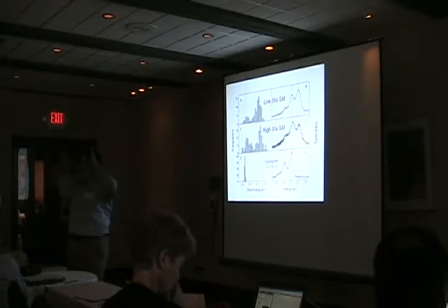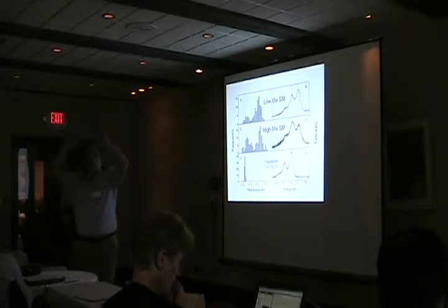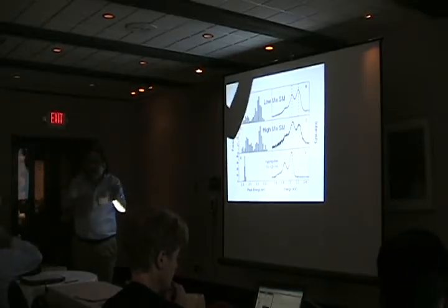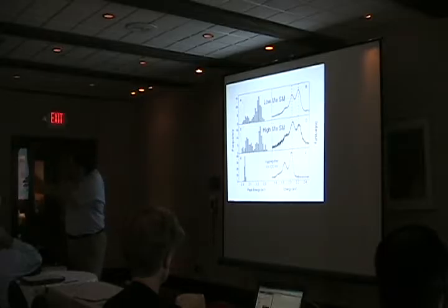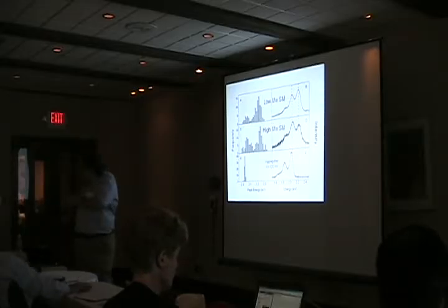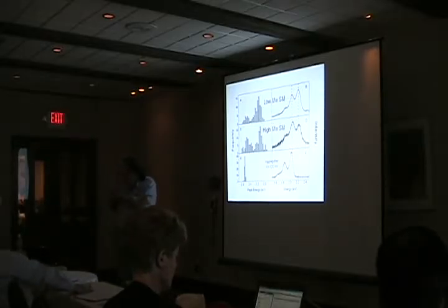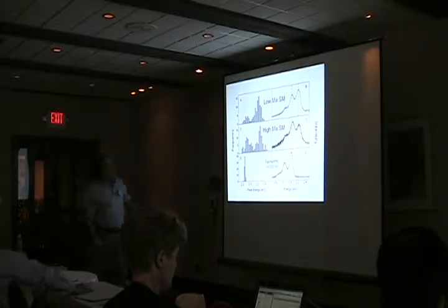Because if you average over a piece which is big enough, if you sum over a piece which is big enough, it's going to be the same whether you look here or there or here or there. You've reached the bulk limit. You only get this spreading out of energies when you get small enough that you interrupt an energy transfer, and small enough so you can sample the heterogeneity of the system.